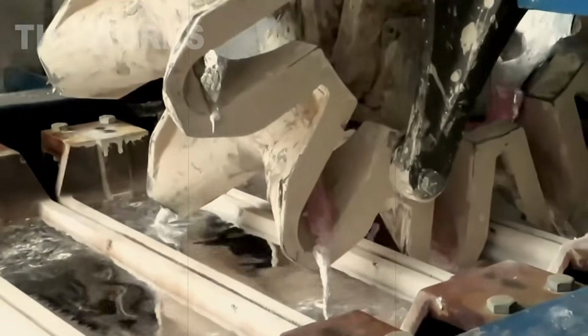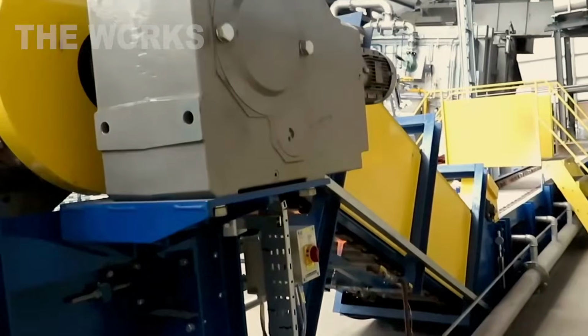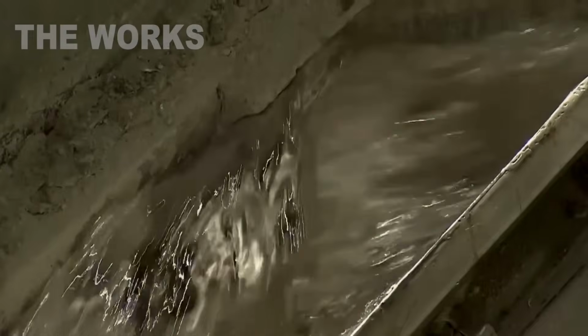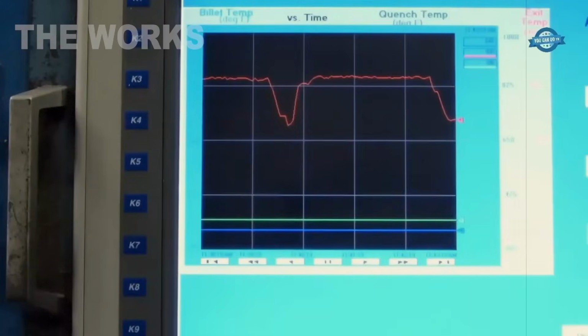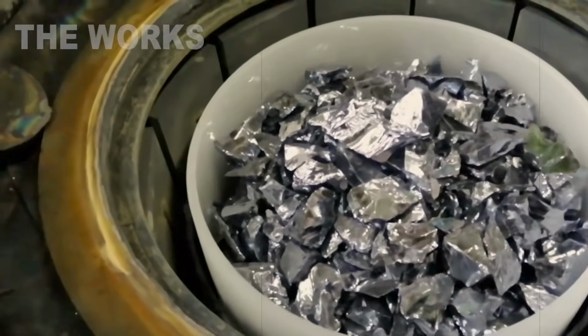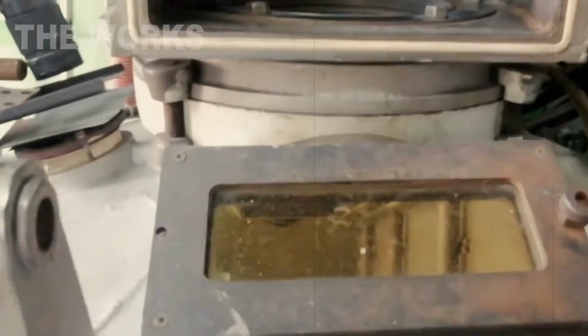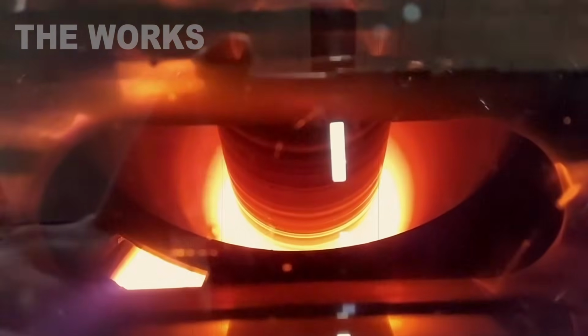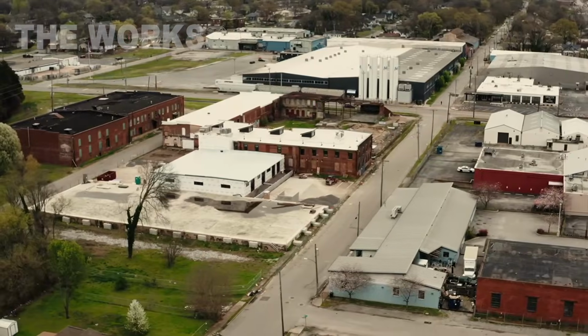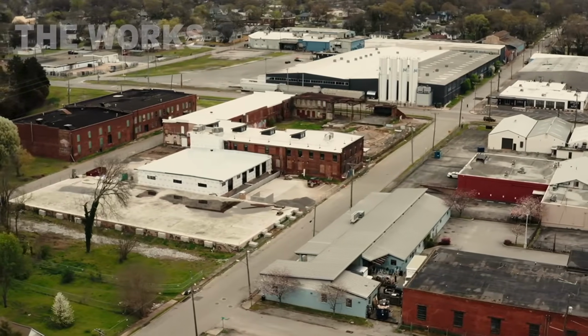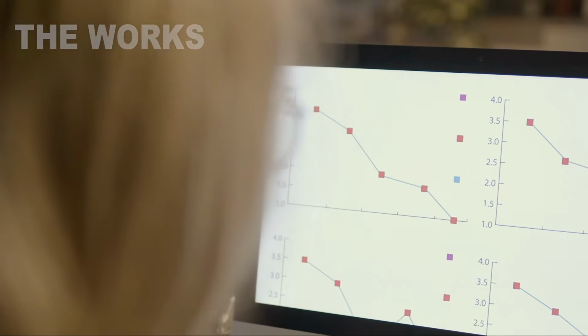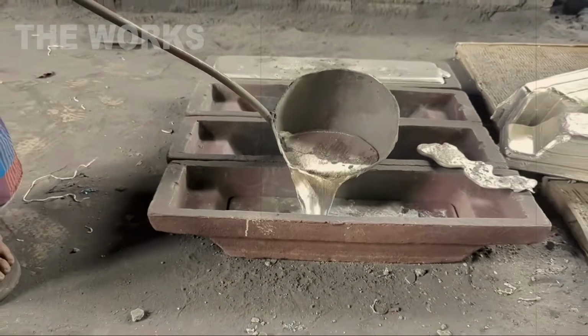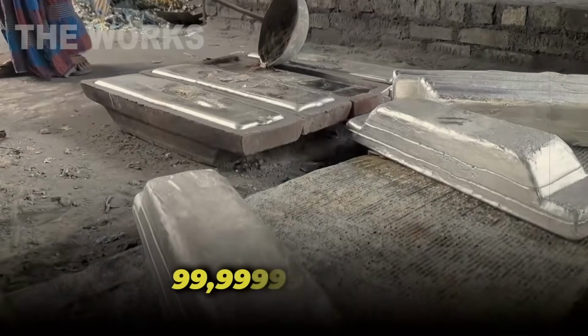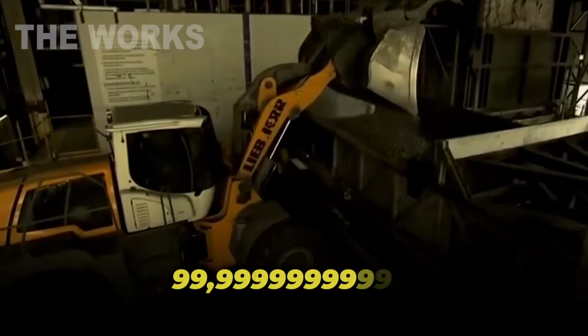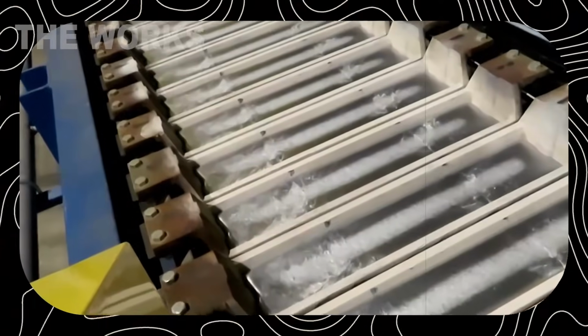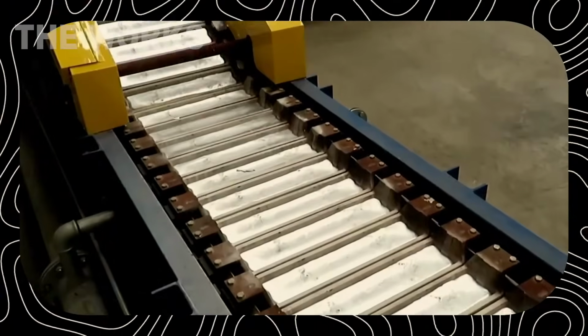This isn't pure silicon yet. This is metallurgical grade silicon, about 98% pure. It contains impurities: iron, aluminum, calcium. For metallurgy or silicone production, that's good enough. But for electronics, absolutely not. Microchips need silicon that's 99.9999999% pure. That means for every billion silicon atoms, there can be no more than 1 impurity atom. Reaching that level of purity is a task that borders on magic.